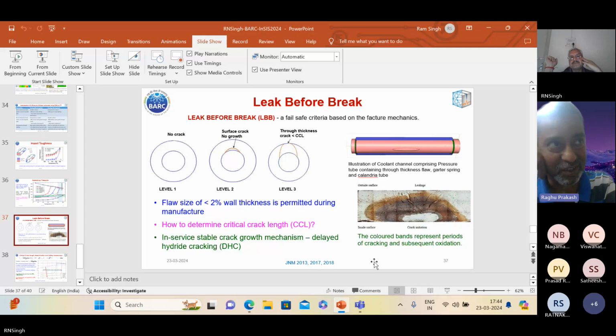By the way, just another question out of curiosity. Did you measure the crack tip chemistry using some kind of sampling technique during any of the studies? As far as DHC is concerned, this is a well-established process. We have not measured it, but we have a plan. Suppose both hydrogen and deuterium isotopes are present. The hydrogen isotope is likely to diffuse much faster. So we intend to measure the isotopic ratio, because if hydrogen is really moving fast near the crack tip, we must get a higher hydrogen-to-deuterium ratio. But so far we have not succeeded in that.